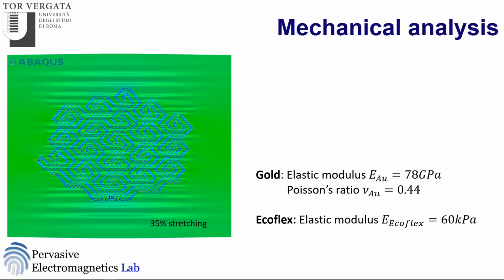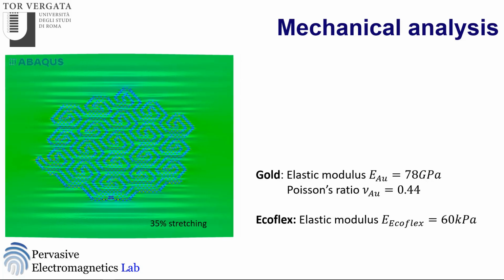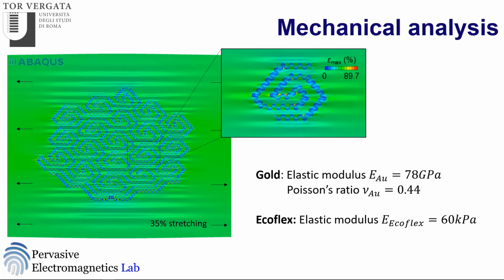The whole structure, namely the gold trace and the Ecoflex substrate, has been stretched on the x-axis up to 35% of its original shape. Then a single shell of serpentine trace is chosen for another finite element analysis. Similar to the larger system, the maximum strain in the Ecoflex elastomeric layer of the smaller system usually exists at the location where the gap opening between the serpentine traces is limited, here reported as red spots.